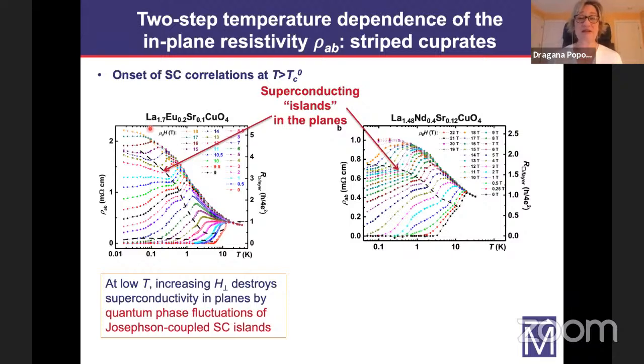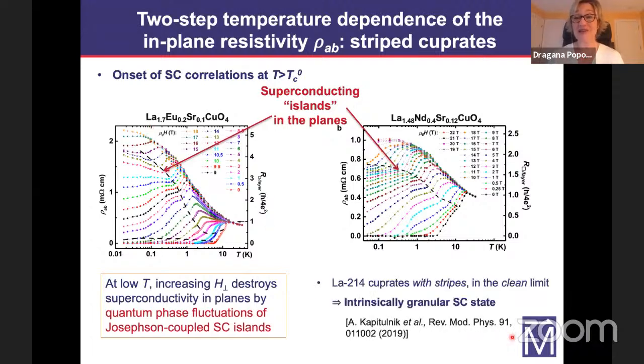So in hindsight, this is actually maybe not so surprising, because these materials are intrinsically granular. There is a nanoscale phase separation. We have charge and spin stripes, and they do not span the entire sample, but they do have a finite correlation length, which is of the order of 100 angstrom. It's also interesting that this kind of possibility was mentioned very briefly near the end of this review paper on failed superconductors, where they said that maybe these cuprates with stripes may give rise to some kind of intrinsically granular superconducting state.